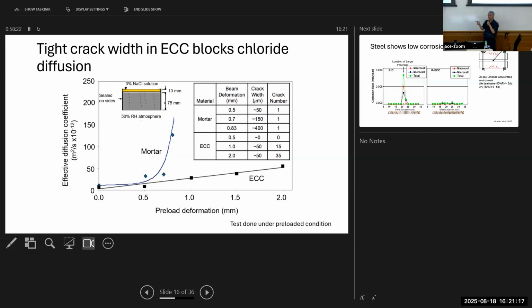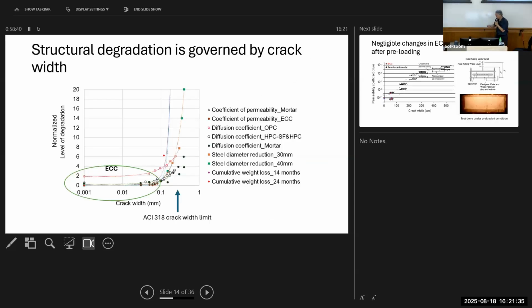So these are experiments carried out in the lab, but we try to simulate the field condition by preloading the specimen before we run the permeability or the chloride ion diffusion tests. And they demonstrate why, for the data that I showed you a couple of slides earlier, it is possible to maintain very good durability, because the material self-limits its crack width.